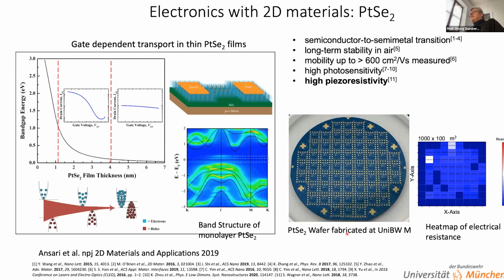And the second interesting point about this material is that PtSe2 has a transition from being a semi-metal in the bulk region, with thickness going down, towards indirect band gaps; a semiconductor opens up below 3 layers. The band gaps open up, so we have a transition here, which always formed the idea that you have a transistor which could be contacted by thick semi-metallic platinum diselenide contacts going into a thin channel, which is then semiconducting, which is sort of shown here in studies, and we could show this experimentally.